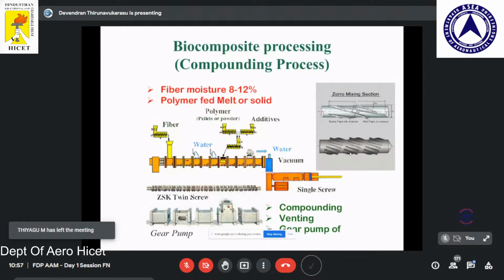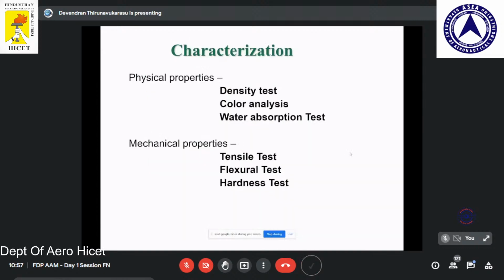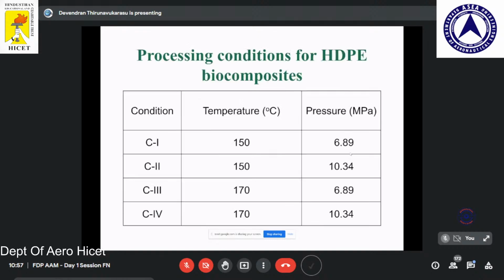Here we need to evaluate the physical and mechanical properties. We study color analysis and water absorption tests for the physical properties, and tensile, flexural and hardness tests for the mechanical properties. We consider optimizing the processing conditions of the high density polyethylene biocomposites, with various temperatures and pressures. The temperatures are 150 and 170, and we selected two different pressures, giving conditions C1, C2, C3 and C4. The sample ID indicates the fiber loading: 10%, 20%, 30%, and pure high density polyethylene samples.